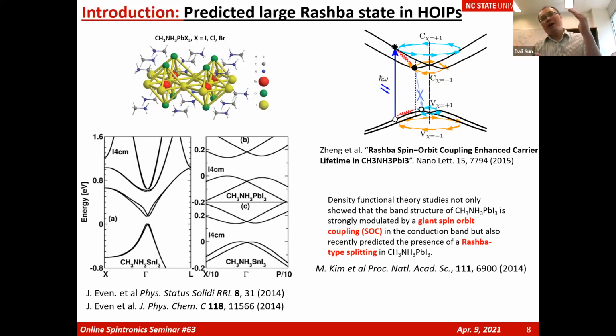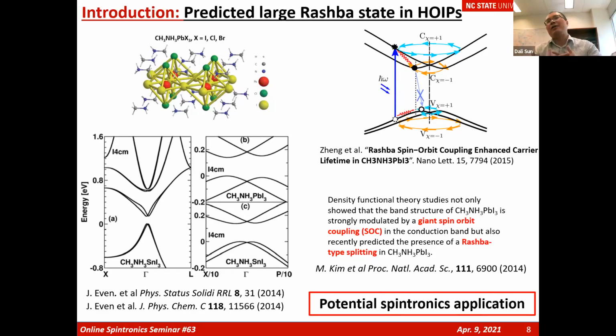He shows a very large Rashba effect by the calculation, but some other groups using different DFT calculations demonstrate the Rashba splitting is negligibly small. So I wanted to comment on why there is a difference between different materials or different methods using DFT calculations. Probably it's the different way to calculate these electronic structures. Typically, I was thinking it's related to the orientation of organic ligands, because once organic ligands relax, they will change the lattice. So with different relaxation of organic ligands during the calculations, your symmetry breaking will be destroyed, and you will have different electronic structures even for Rashba states.